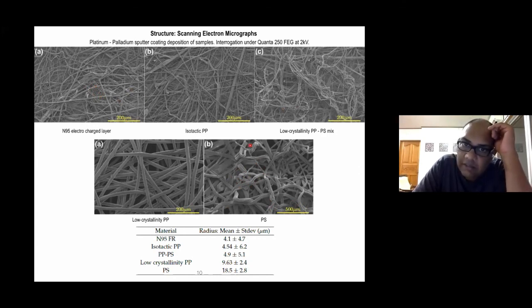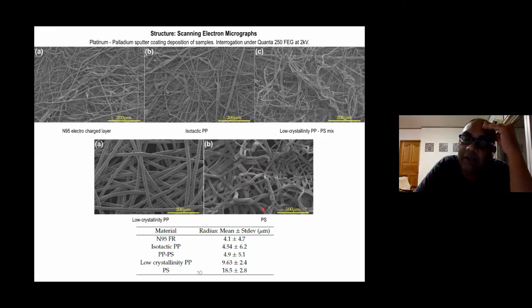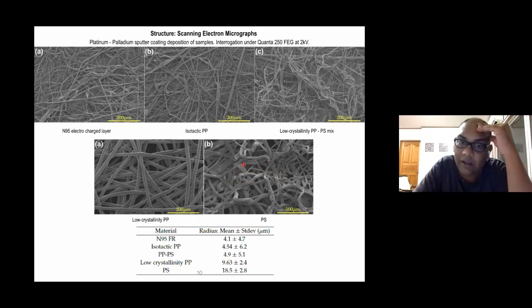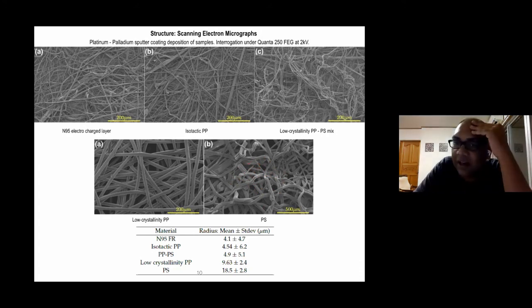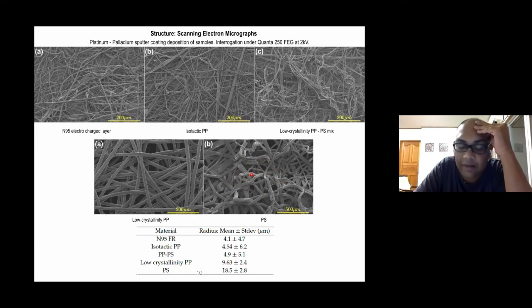Because it is a crystalline material, whereas polystyrene is a glass, and once you go past its glass transition temperature, its viscosity is very sensitive to temperature. So I'm sure that if I play with the polystyrene material, I can get fibers of much smaller radii with the same tortuosity, and it has much higher electret charge retention characteristics. So you're absolutely right. I think the way to go would be polystyrene, if I can figure out the right temperature.